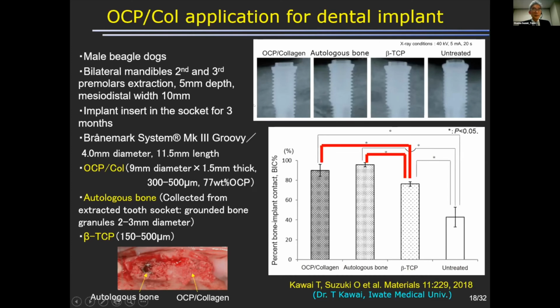And you see after the 3 months, although the untreated group still has a radiolucent zone, these 3 groups have very high radial opacity. And if we look at the percent bone implant contact, the OCP collagen and autologous bone have higher BIC percent compared to beta TCP and also the untreated group. So OCP collagen alone has the capacity to form new bone in the clinical situation in the experiment.